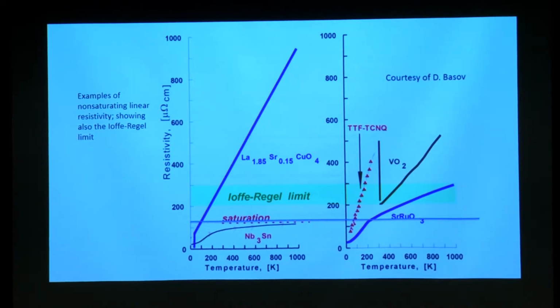Fine. So here I show the resistivity of some metals as a function of temperature. This is lanthanum cuprate. You notice that its resistivity increases linearly without showing any signs of saturation or leveling off. And here is the Mott-Ioffe-Regel limit. It's a band, it's a crossover. It's not a very sharp, precise number, but it is sort of expected to be in this range. So you see that the resistivity increases like that.